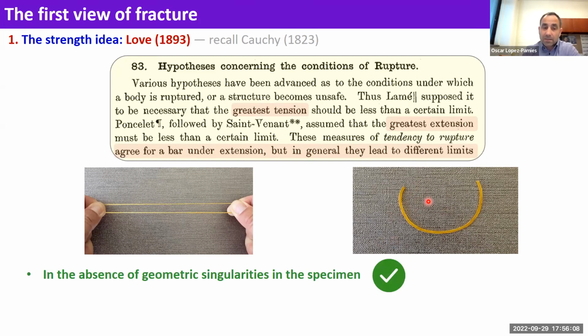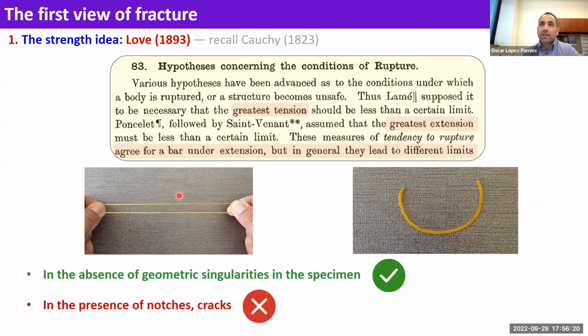However, they realized that this is great if there are no singularities in the structure. If you start to consider structures with sharp corners or with cracks in them, these fail miserably. The reason is that if you have a geometric singularity in a structure, the stresses are infinitely large at the singularity, right? If you think of a sharp corner, the stresses there, the moment you touch it, are infinitely large, which would imply that it should break right away, but that is not what happens, right? So this idea worked, but only partially.